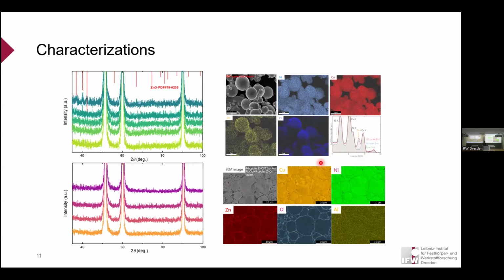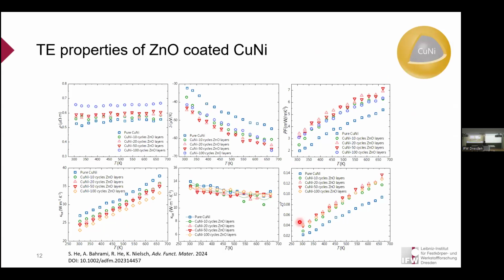And we can see the coating through the mapping. You can see a very, very uniform coating. And even after sintering, we can see the patterning of oxygen follows very nicely at the boundaries. So that means we could effectively coat the surfaces of these particles and form some kind of scattering effect. And we look at the transport. Here is an example of zinc oxide. We can also look at aluminum oxide and layered material, but that's too much information. This work has been published here, and if you're interested, of course, you can go read it.